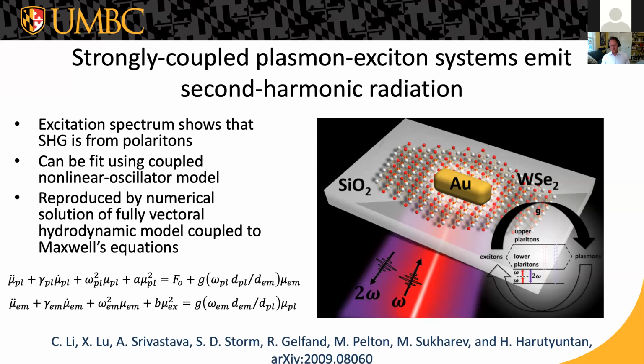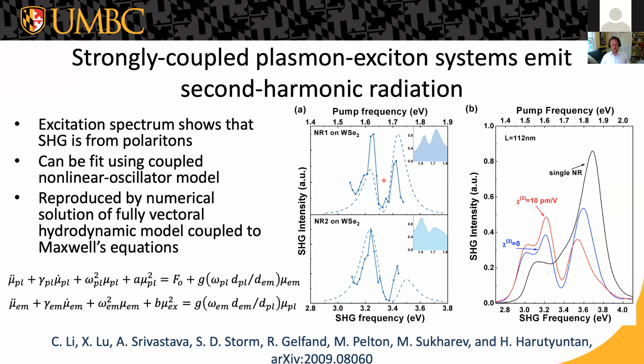And the goal here was to go one step further and look not just at the linear spectra, the scattering or photoluminescent spectra, but to look at the second harmonic spectrum, the nonlinear spectrum of this. So what they do basically is take an excitation laser and tune it across the plasmon and exciton frequencies here. And what we're seeing in these graphs is the intensity of the second harmonic signal that comes out as the excitation laser is tuned across this system. You can see there are clearly two peaks in the second harmonic excitation spectrum. So the second harmonic is coming not from the isolated exciton or plasmons, but from these hybrid polaritons inside the system.